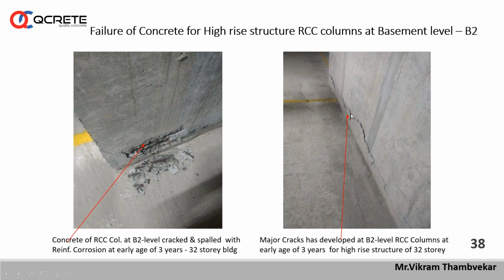Here in another picture we can see cracks have developed at the same level, and at the same lift wall or some very big columns, because for high-rise buildings column sizes at lower levels are quite big, in some cases 1 meter or 2 meter, and of course the width is also 230 or 300 or something. So when there is a high volume in a column, retaining wall, or lift shaft, all the people working at site should take care to compact in a proper way, and of course the casting depth of such a column, lift shaft or retaining wall should be limited to 1 meter only, or not more than 1.5 meter.